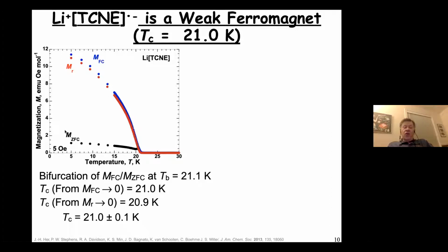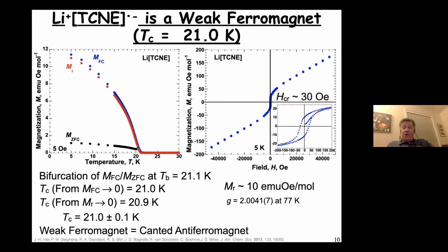And we can see that if we look at the low field, field cooled, remnant and zero field magnetization, there's a near coincidence of the field cooled and remnant magnetization and a bifurcation with the zero field magnetization, indicative of magnetic ordering at approximately 21 degrees Kelvin for this material. If we look at the M of H curve, we do not see saturation. We see a small remnant magnetization around 10 EMU Oersteds per mole. And this suggests a weak ferromagnet or a canted anti-ferromagnet, depending on what term you like to use for it.